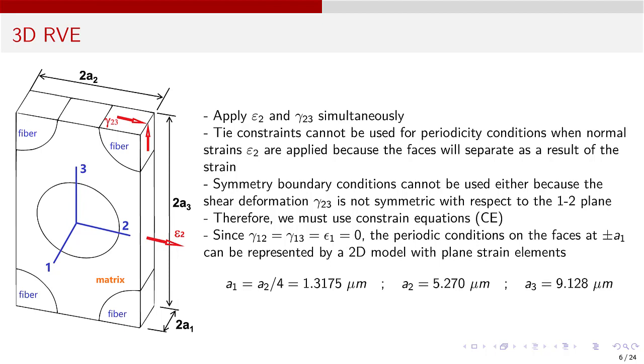For this example, the fiber direction strain epsilon 1 and the shear strains gamma 12 and gamma 13 are zero. That allows us to reduce the domain from 3D to 2D, applying periodicity on the front and back faces using 2D plane strain elements. And if epsilon 1 were different from zero, we could use 2D generalized plane strain elements.